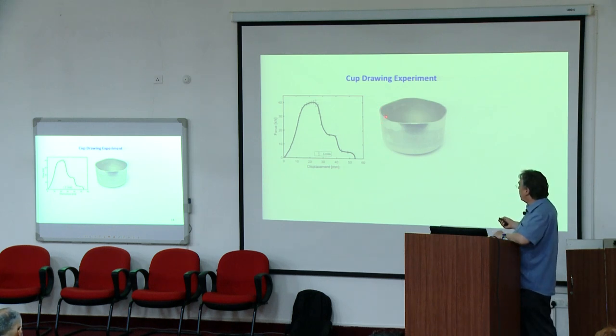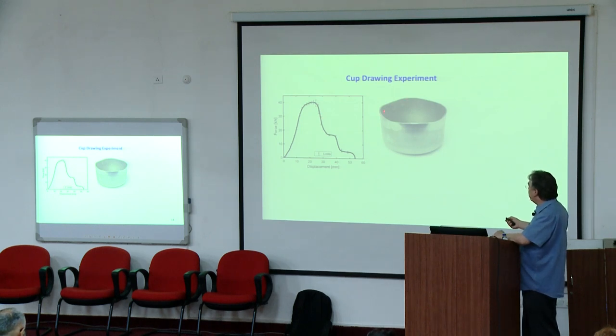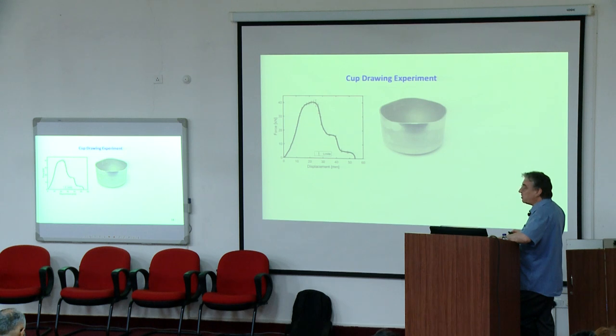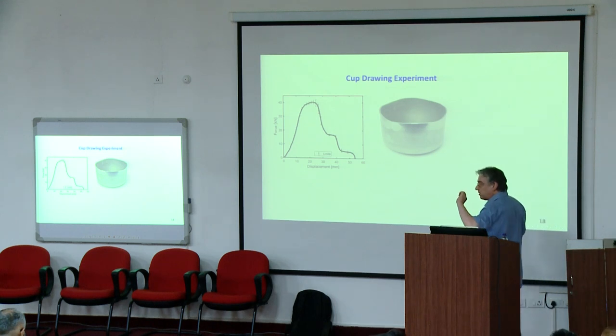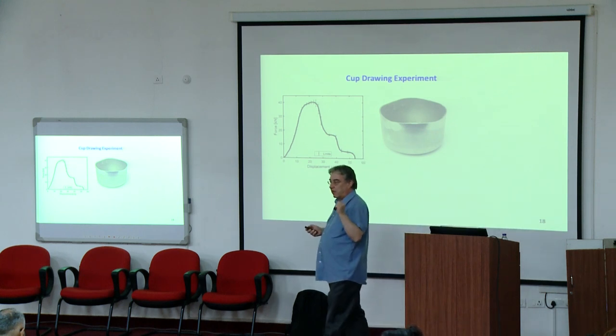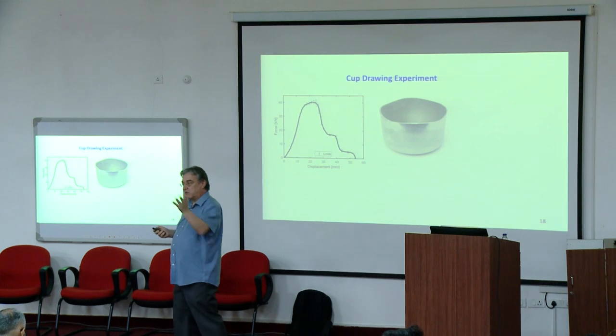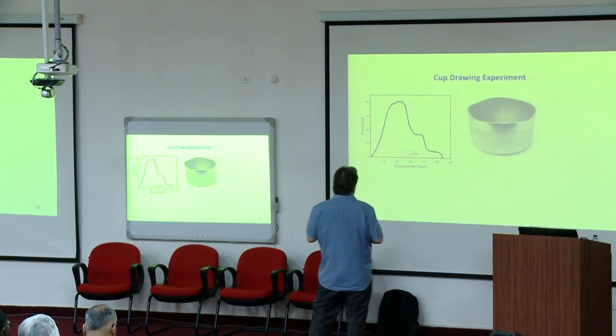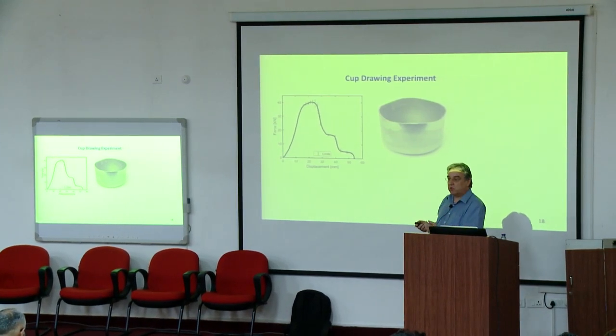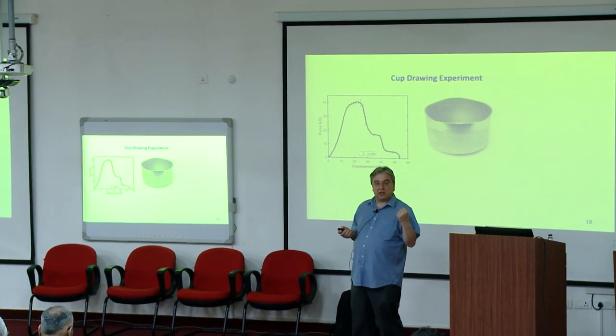And what is important, this is a force displacement curve. So you see that first the force goes up and then goes down. And you have also here the edges, what are called the ears. For industrial application, these ears should be as small as possible because they have to be trimmed. And this is, of course, expensive, lots of material, because you have to do this trimming operation. So it is very important for industrial applications to be able to predict this earing reliably, and to be able to predict it for many different steel and aluminium grades.